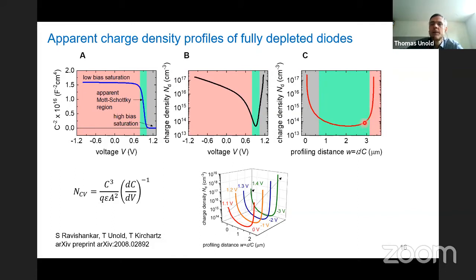So basically here you increase the reverse bias, but nothing happens with the capacitance. And here you have injection of carriers in your device and you get this artificial shape. And then you have a region here where it's maybe okay. And if you look at it, here are different curves shown for different forward and reverse biases used. You can see the further you go in reverse bias, the higher up you go here. And the further you go in forward bias, the higher you go up here.